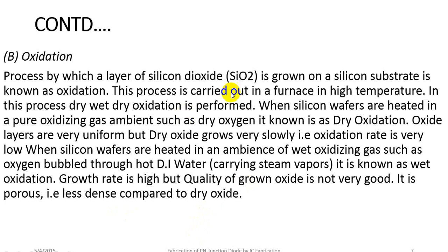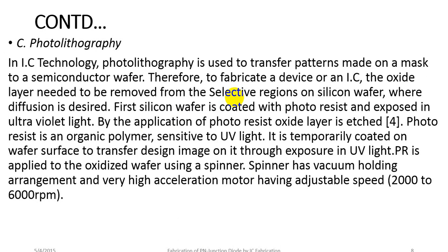The third process is photolithography. In IC technology, photolithography is used to transfer patterns from a mask onto a semiconductor wafer. The oxide layer needs to be removed from selective regions where diffusion is desired. The silicon wafer is coated with a photoresist and exposed to ultraviolet light. Photoresist is an organic polymer sensitive to UV light, temporarily coated on the wafer surface. It is applied using a spinner with a vacuum holding arrangement and a high acceleration motor running at 2,000 to 6,000 RPM.